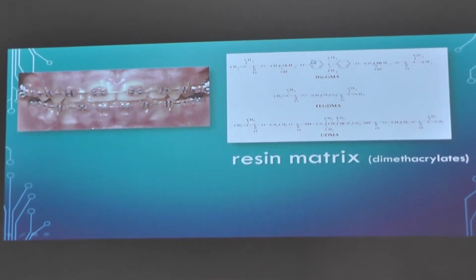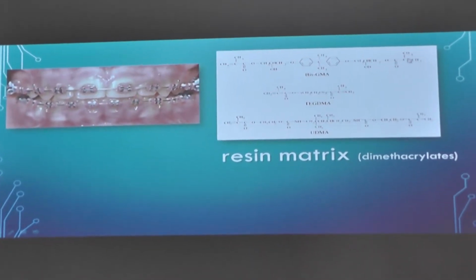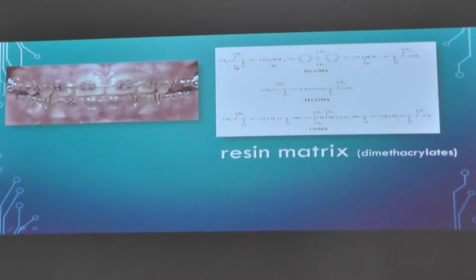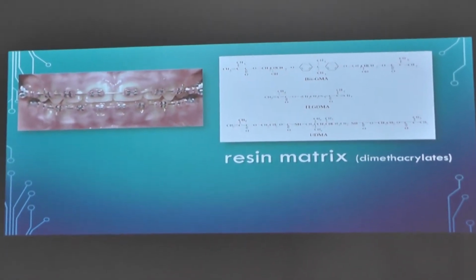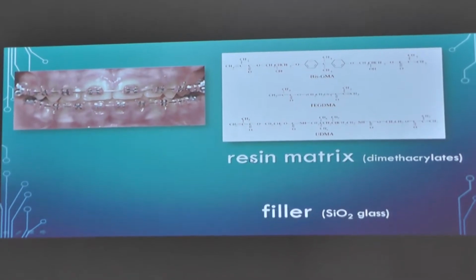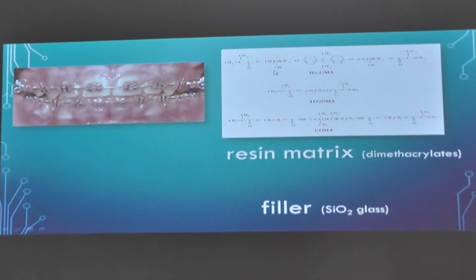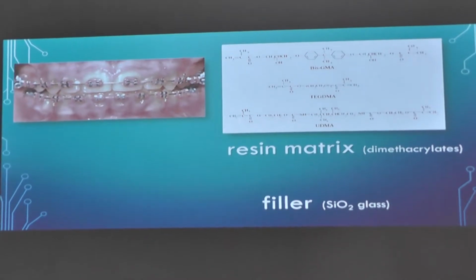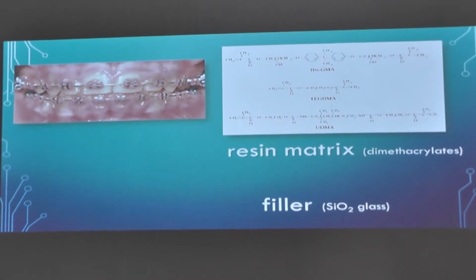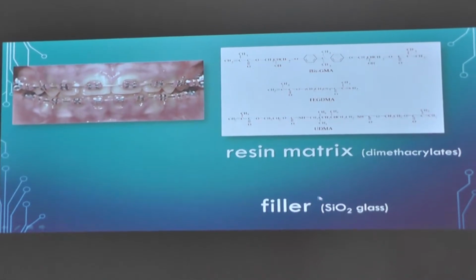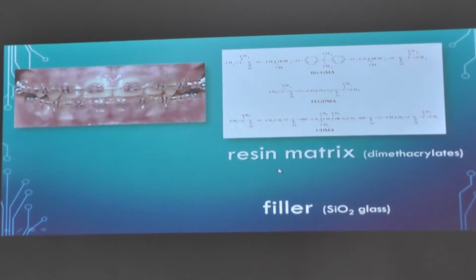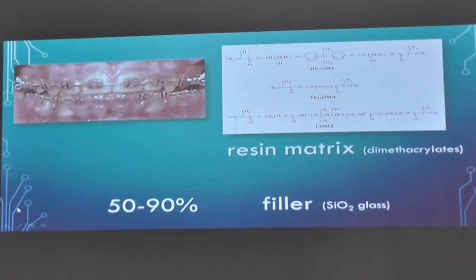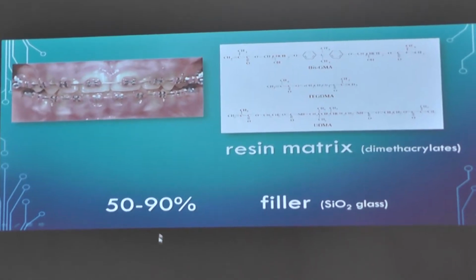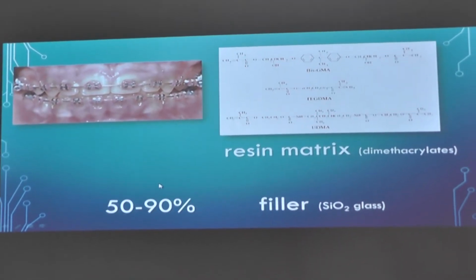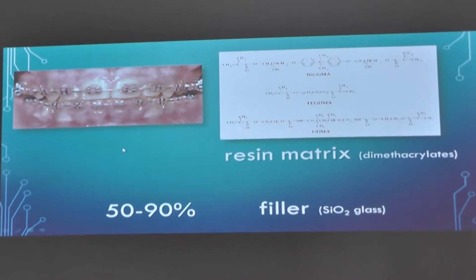It has monomers that at their ends have double carbon bonds and can form long chains. This is something you all already know. But again, even when polymerized, the resin matrix itself is not stiff and hard enough, so it needs a lot of filler to withstand the forces that we talked about, and it is silica glass with addition of some ions if necessary. We will talk about that later. So orthodontic adhesives have a very high content of filler in comparison to regular adhesives in restorative dentistry.